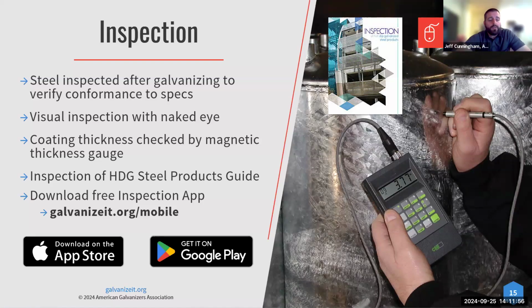Inspection is scrutinized on all galvanized pieces, obviously, for conformance with specifications. Specification ASTM just dictates adherence, coating thickness, and any maximum bare spots. So it's usually done with a visual inspection with the naked eye, making sure there are no bare spots or anything like that. You can get a coating thickness reading by using a magnetic thickness gauge.